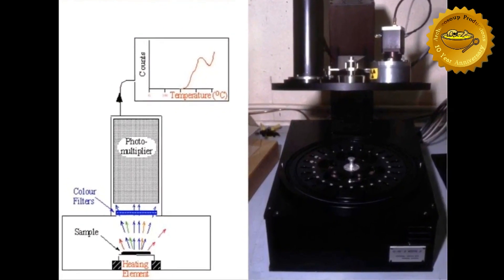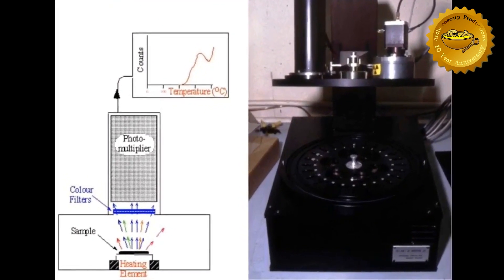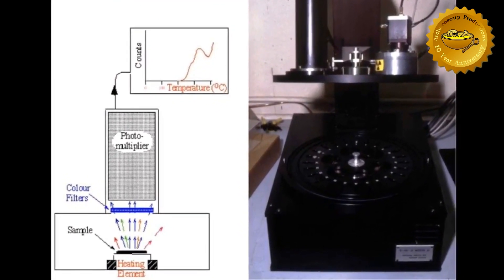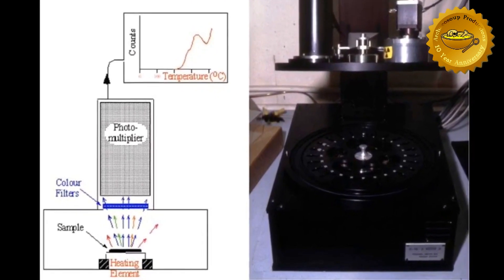When a sample is taken and rapidly heated, it is possible to measure the energy or light emitted, and thereby gain an estimate for when the pot was last exposed to heat. So archaeologists, being the clever sort we are, have been able to apply this observation to archaeology and use it as a way to date certain objects.